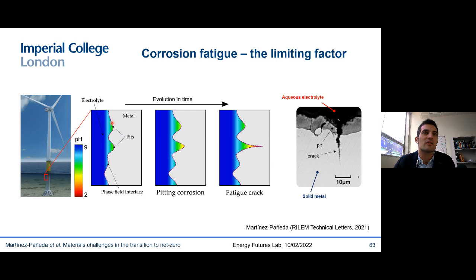First, you have corrosion pits that originate at the seawater electrolyte interface, the seawater metal interface. These pits grow, driven by local chemistry and mechanics, and eventually you have a pit to crack transition event, and fatigue cracks will propagate until the failure of the sample. And there are two challenges here. First is predicting the evolution of this complex morphology, the morphology of this interface. And the second challenge is the strongly coupled nature of this phenomenon.